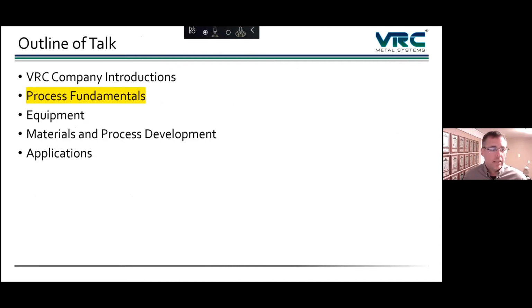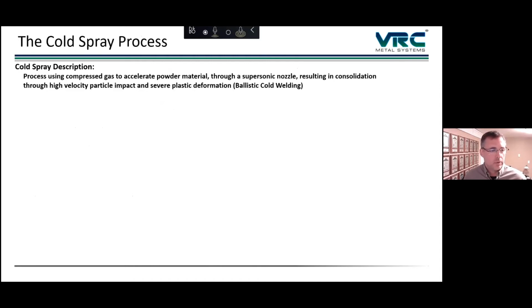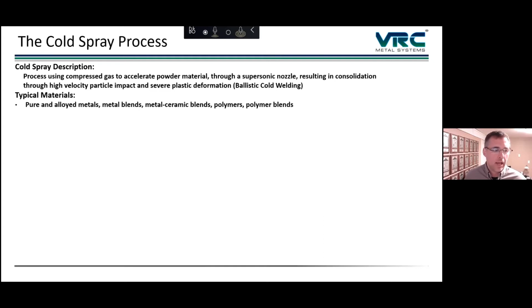All right, so now let me get into what this process is all about, this cold spray process. So we take a compressed gas and we accelerate powder through a supersonic nozzle. And when we do that, we consolidate that material through a severe plastic deformation when it impacts on the substrate. So this is like cold welding, but it's happening at a very, very high strain rate. So this works really well for metals. There's a lot of pure and alloyed metals that have been sprayed by us and by others. This is probably the bread and butter for this process.